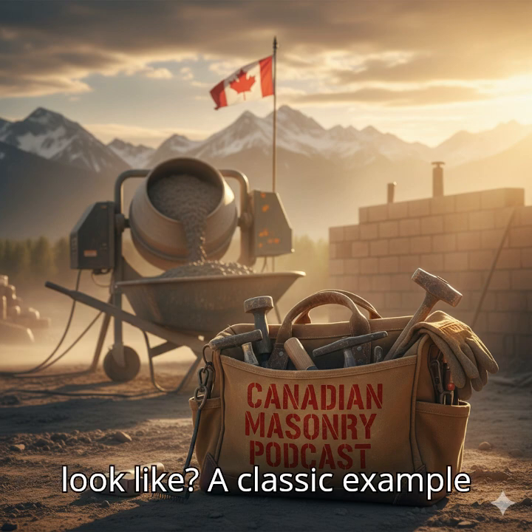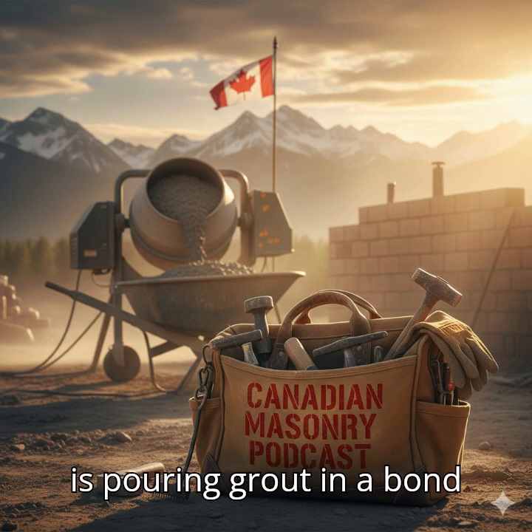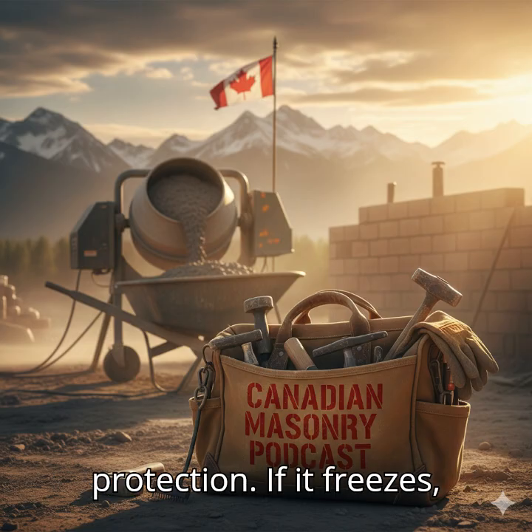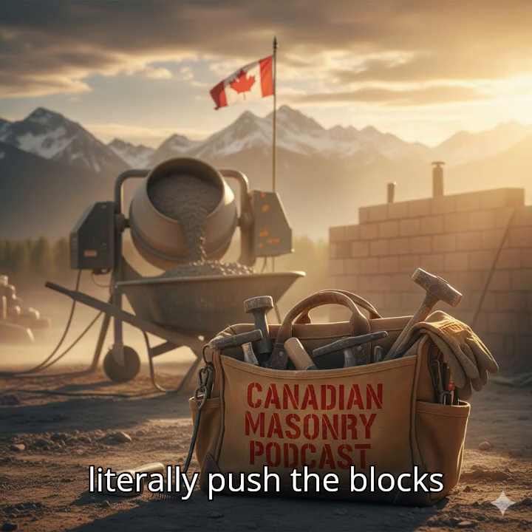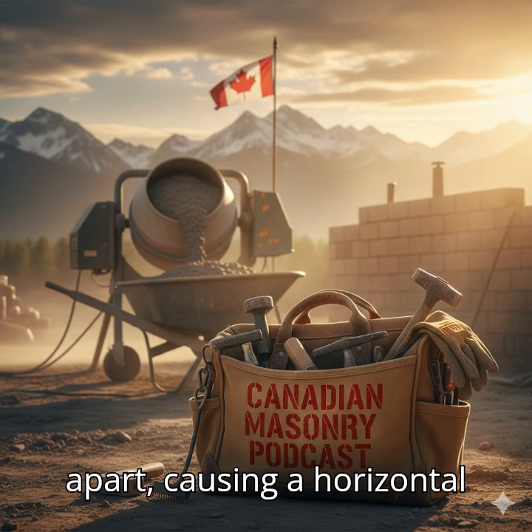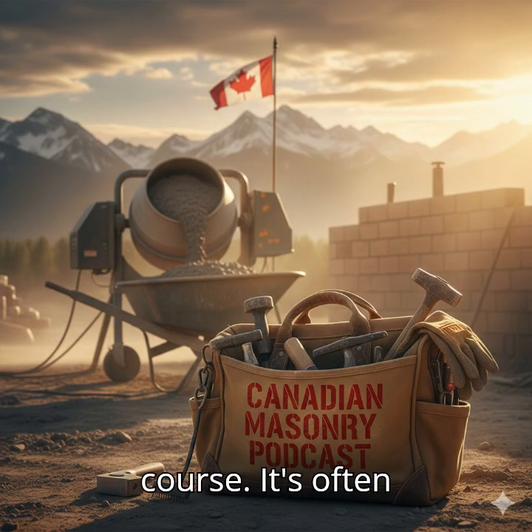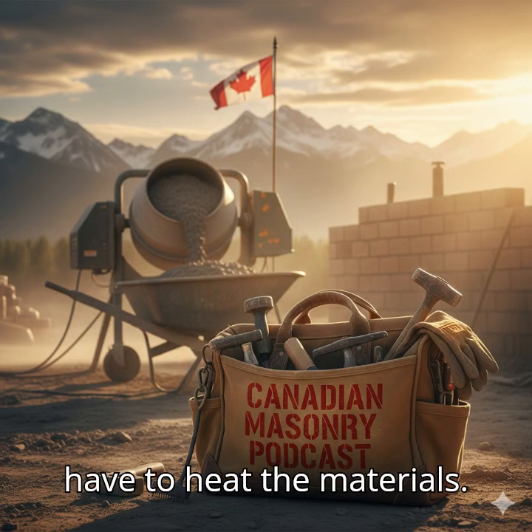What does that damage look like? A classic example is pouring grout in a bond beam on a cold day without protection. If it freezes, the expanding ice will literally push the blocks apart, causing a horizontal crack right along that course. It's often irreparable. So contractors have to heat the materials.